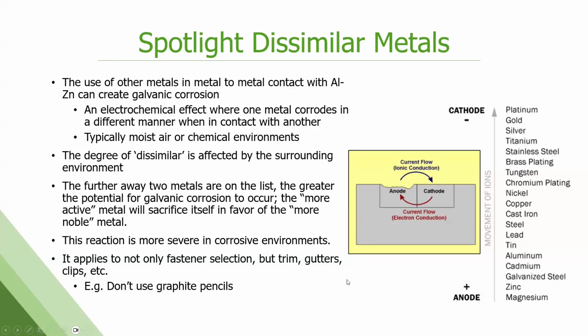So we see stainless fasteners used a lot, and they're a great choice in 90% of the environments they get used in. But if it's a marine type environment or a heavily corrosive environment and you've mixed stainless with this product, the aluminum zinc product is going to sacrifice itself at an accelerated rate to protect the stainless steel. So there's a lot of information out there around proper fastener selection, trims, gutters, what to mix, what not to mix, to avoid early failure.